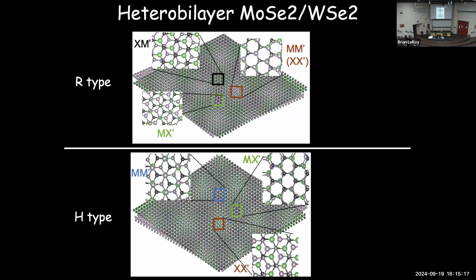So that's what happens when you take a homobilayer, two of the same materials, and stack them on top of each other. You can also do the same thing with a heterobilayer. So in this case, instead of 2 layers of tungsten selenide, we replace the top layer with molybdenum selenide. And so the same kind of stacking configurations, 0 and 180 degrees, turn out to work here, and you get roughly the same type of stacking configurations.